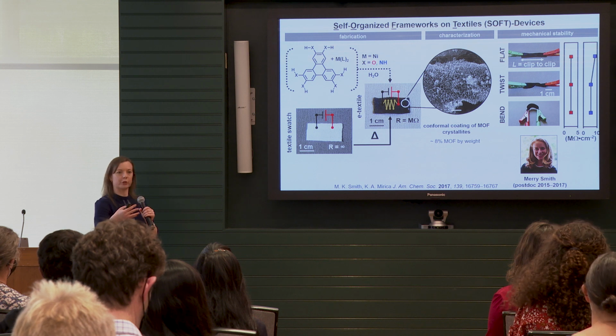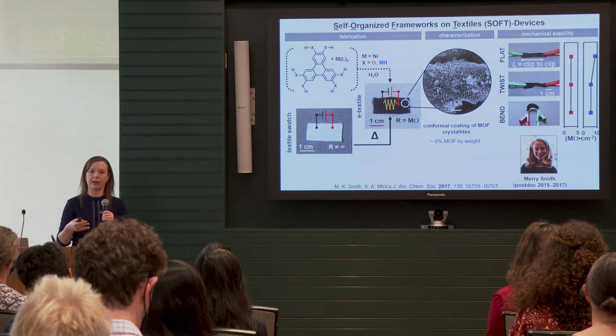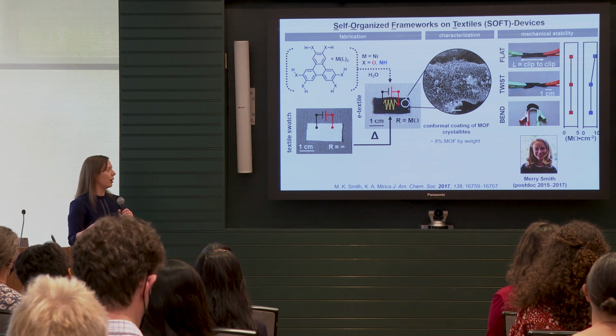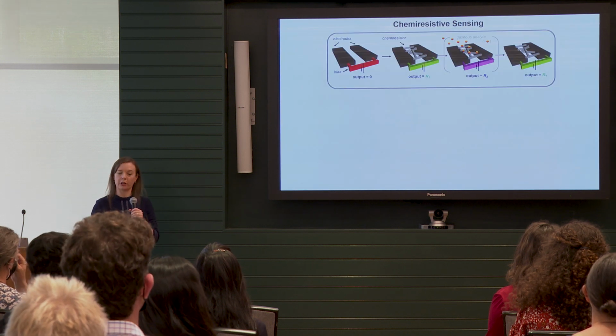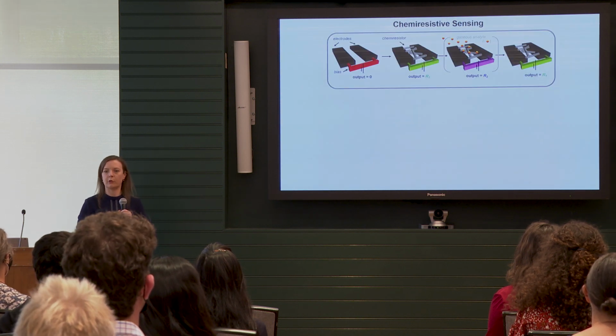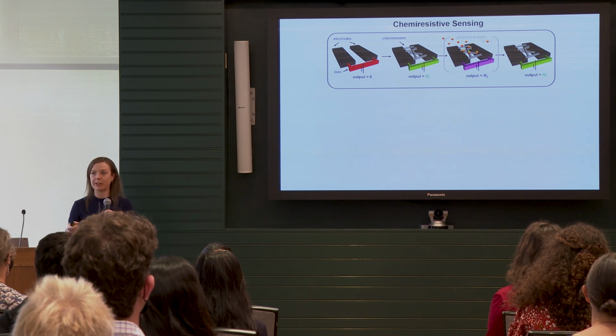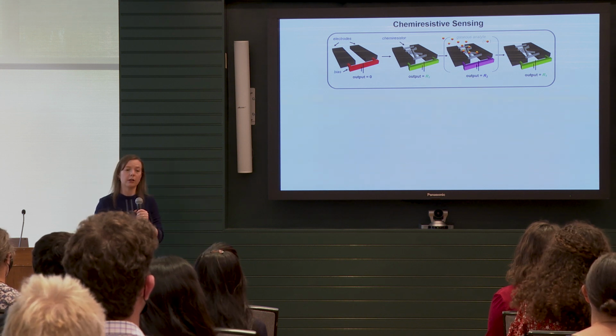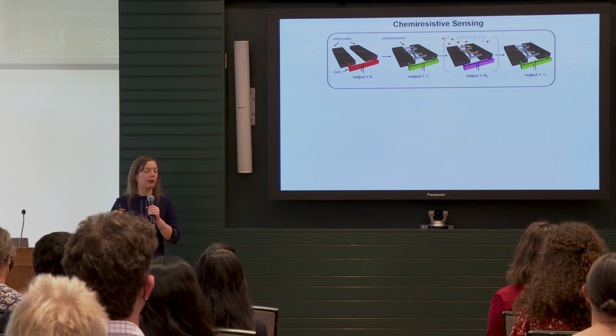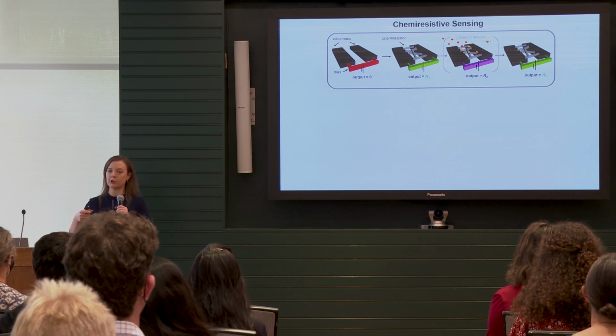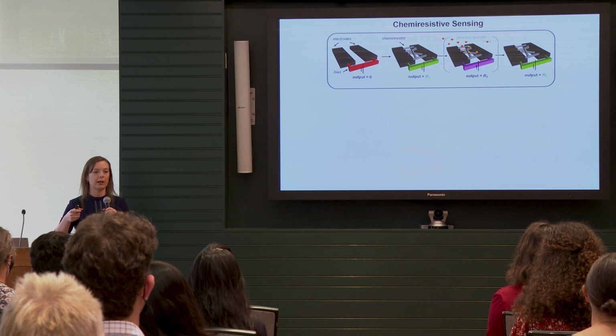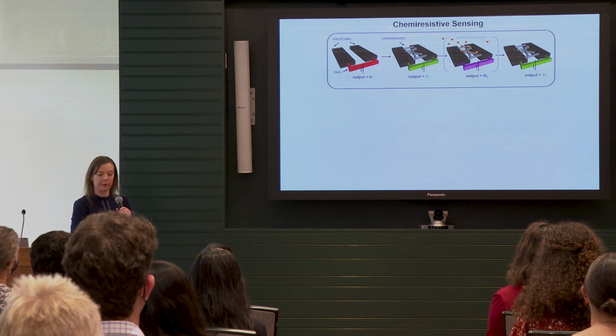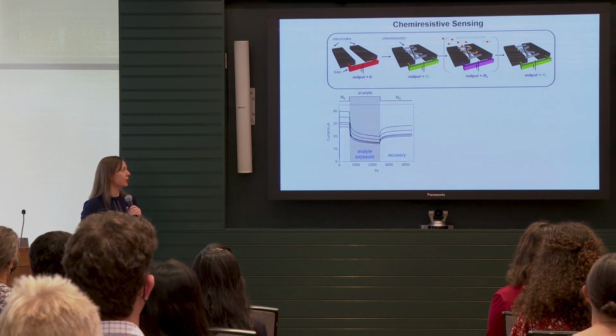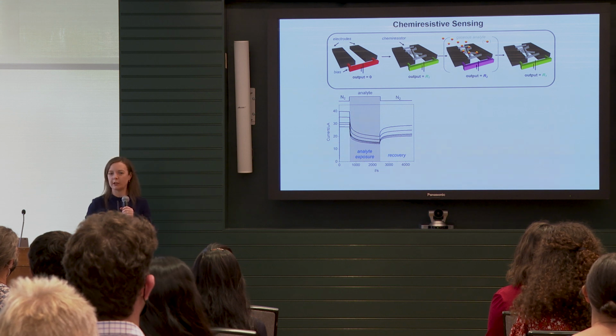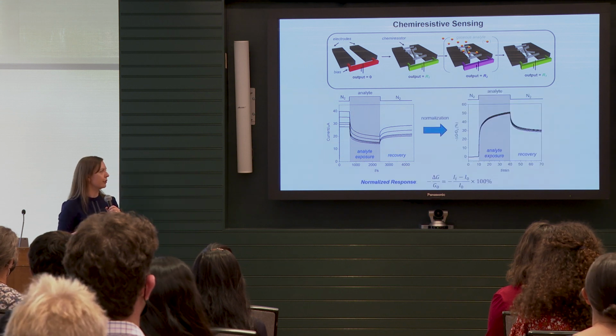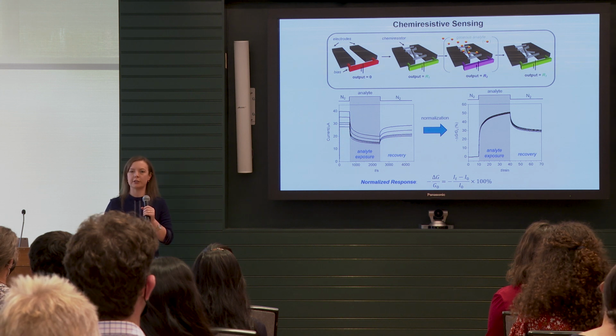Then what we do in terms of probing the sensing function of this type of electronic textile is apply voltage and measure current. And this constitutes one of the simplest chemical sensor types of devices, which is known as a chemiresistive device. In this device, we hook up our material between two electrodes, and we apply voltage and measure current. So this is a constant voltage measurement that generates a current versus time plot. We then take that plot, deconvolute it, and basically normalize it to generate a sensing response.